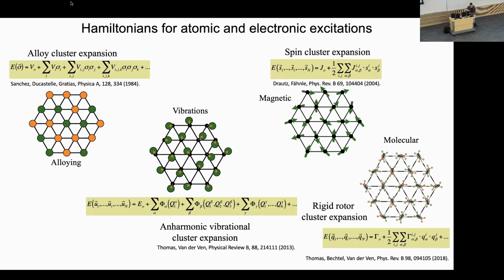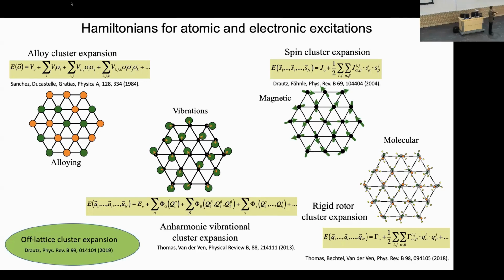It was recently extended to off-lattice descriptions and shown that most of these machine-learned interatomic potentials that are now very popular are actually approximations of a generalized off-lattice cluster expansion following the same math. So a lot of these machine-learned interatomic potentials is really just rigorous math, but done in an indirect way with fancy machine learning tools that are now available. But essentially, all these tools of extrapolating DFT methods can be formulated in terms of these cluster expansion techniques.